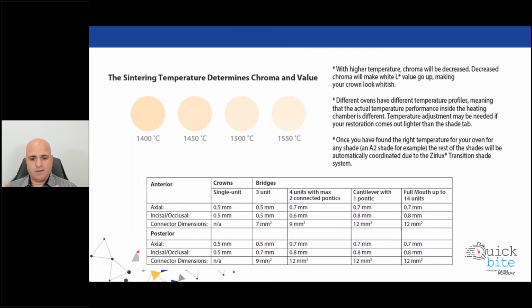Every sintering oven, even if it's the same brand, doesn't necessarily work the same way as another sintering oven. Just like ceramic ovens, we've learned to calibrate and utilize ceramic ovens. Now we have to relearn how to do that with the sintering ovens, because just because the temperature says a certain amount on the digital display does not necessarily mean that that's the temperature on the inside of the chamber. So by calibrating it, and it's a very simple process, there are calibration rings, and I know Zahn sells them as well. It's the Transitions Zirlux rings, and you place the ring into your regular sintering oven, and once it cools off with your restorations, you remove the ring and measure it, and its geometric shrinkage will correlate to what the temperature was of the chamber.